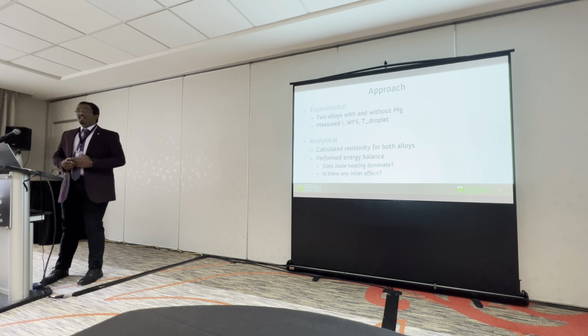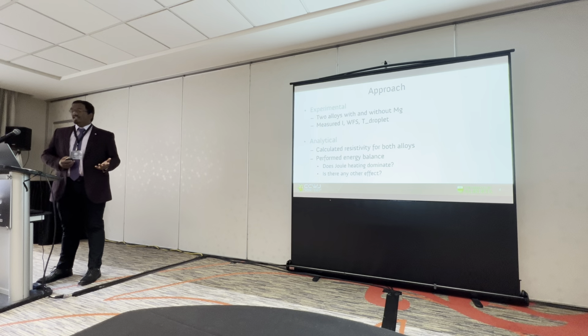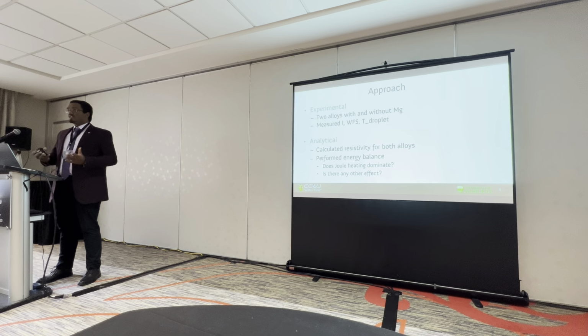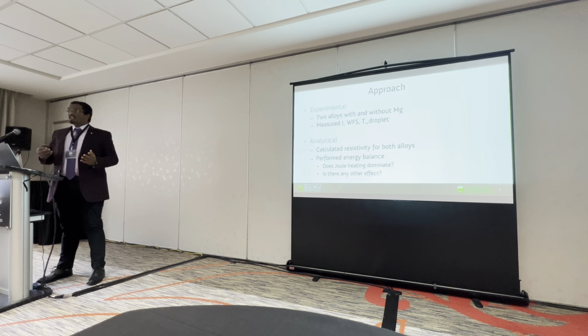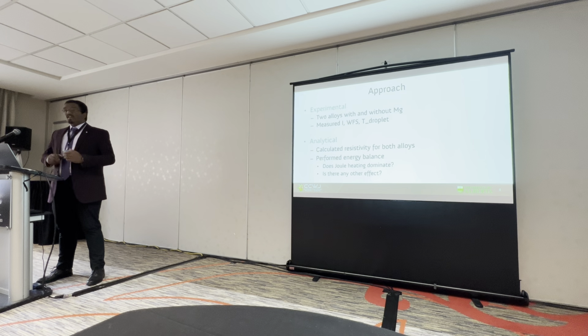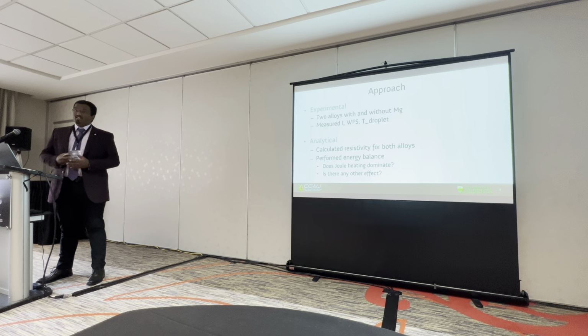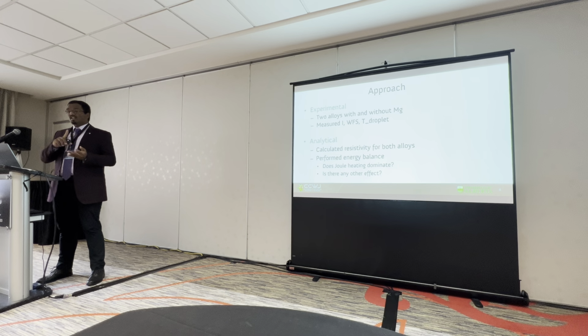For the approach, I take a two-step approach. The first is the experimental aspect, in which we consider two alloys, one with and without magnesium, to understand the impact of magnesium, and we also measure the current, wire feed speed, and the droplet temperature. In the analytical aspect, we calculate the electrical resistivity for both alloys. We also perform an energy balance of the entire system to understand how much power is necessary to melt the wire, and how much power would be generated through joule heating. Would the joule heating value be sufficient to take care of the power necessary to melt the wire, and is there any other additional effect which we are not considering?